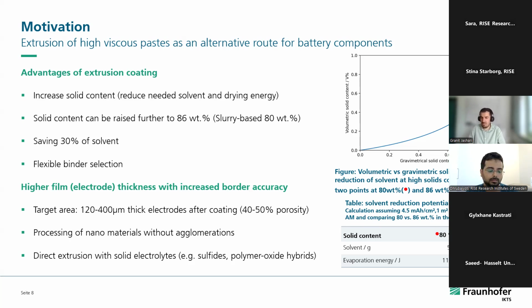So we could make 120 to 400 micron thick electrodes, and after coating the electrodes have a porosity of 40 to 50%. We could process different kinds of nanomaterials without agglomerates, as well as direct extrusion. It's also a good approach for other chemistries in solid state: sulfides, polymer oxides, hybrids.